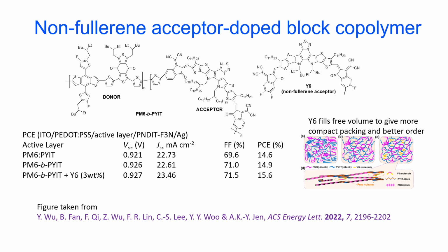And this is a polymer which could either have the donor molecule on its own, just this part in the left-hand bracket, and the acceptor polymer on the right-hand side, two different components blended, and you'll see that gave in the device 14.6%. When you join them together to make a polymer which has got donor acceptor components in the same polymer, plus a non-fullerene acceptor which is blended with the final mixture. So that's the result here. This is the copolymer plus 3 weight% of this acceptor blended into it, what we might call a ternary polymer. They managed to reach 15.6%.